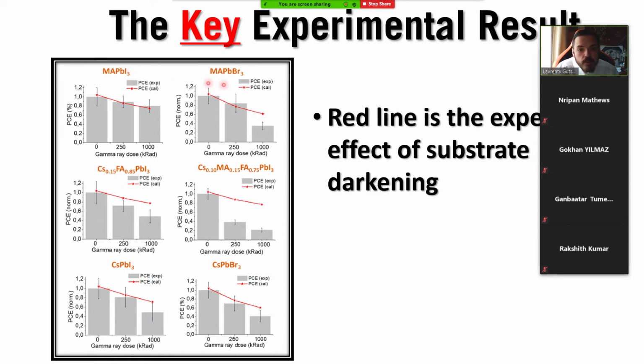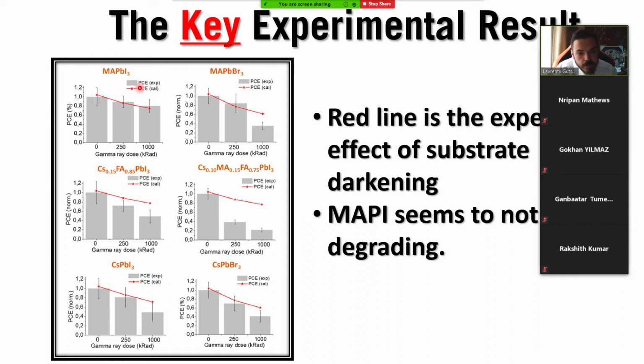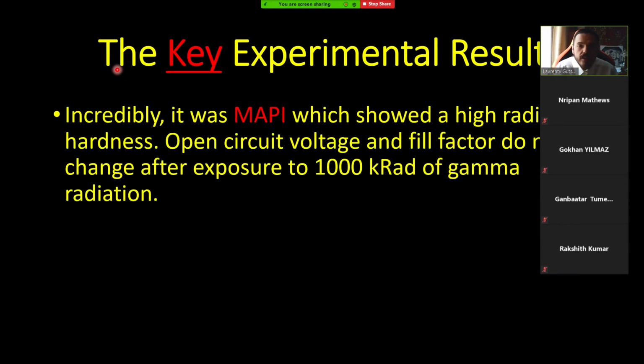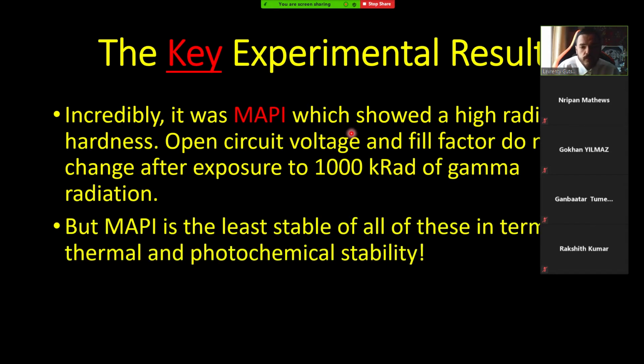So clearly, this is related to the iodine, and that's very surprising because we know that MAPI is typically not that stable a material. It's probably the least stable perovskite on average. MAPI, as I said, has a high radiation hardness. The open circuit voltage and fill factor do not change even after exposure to 1,000 kilorad. So this is basically space levels of gamma radiation. And again, we know that normally MAPI is not stable at all.